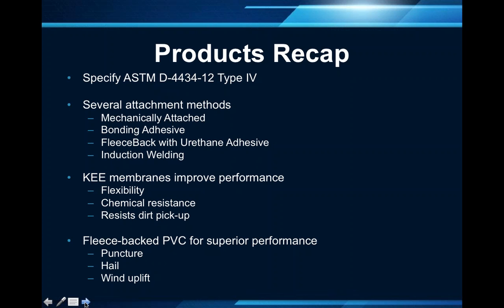Little products recap. ASTM D4434-12 Type 4 has the strongest testing for breaking strength, tear strength, and elongation. There's several attachment methods for PVC. You have mechanically attached systems. You have bonding adhesive and fully adhered systems. You have fleece back available with a urethane adhesive. And then you have an induction welded system.